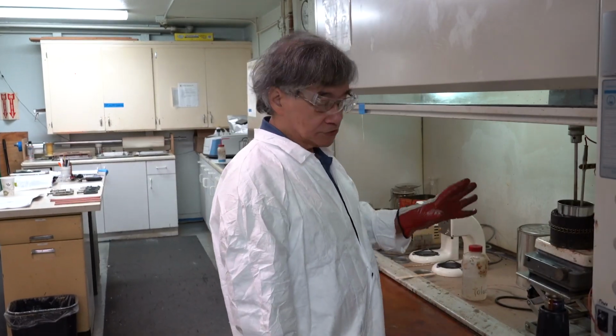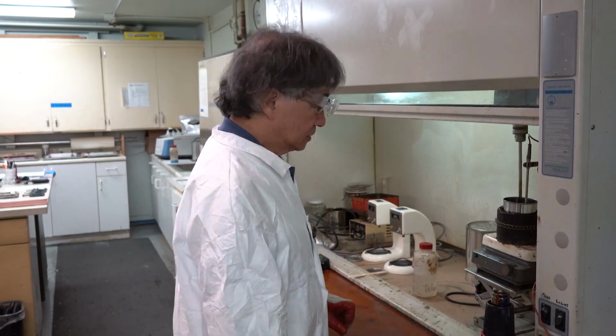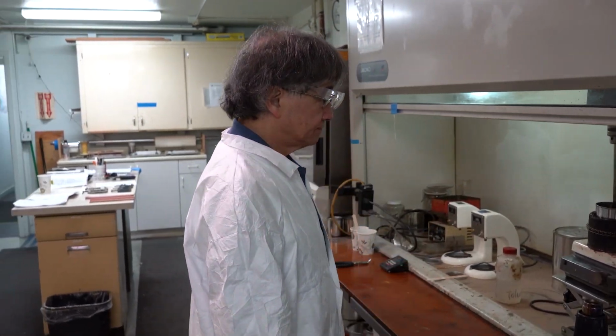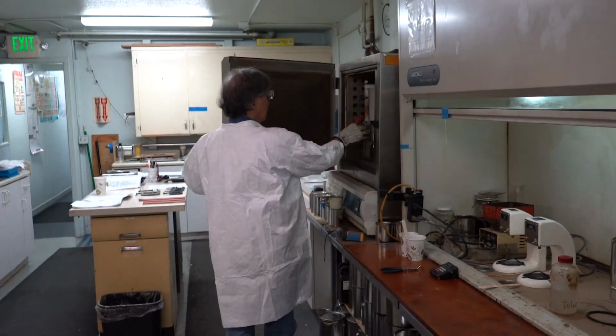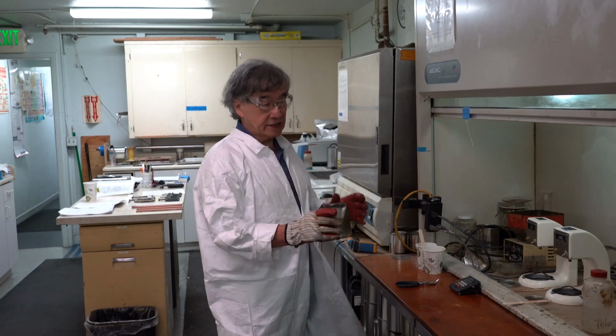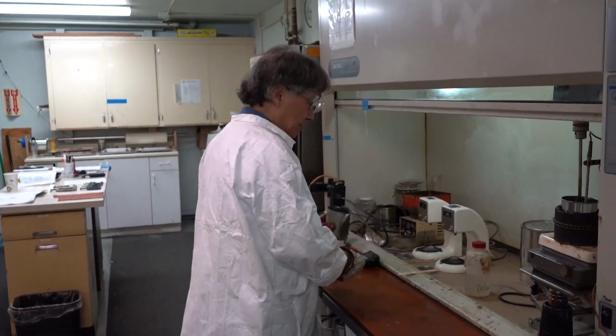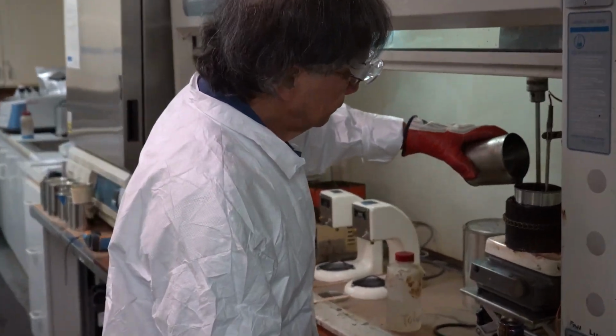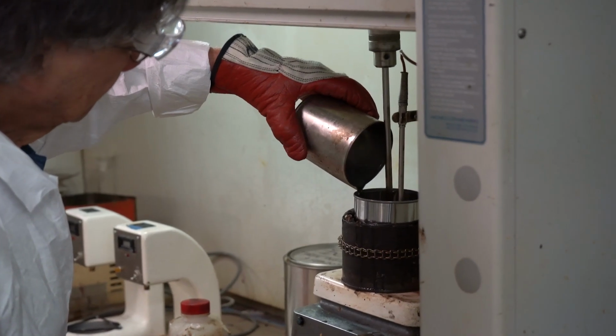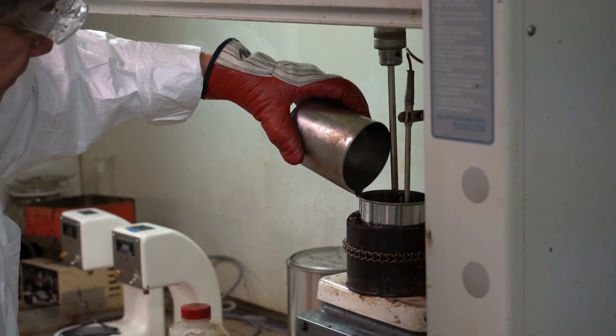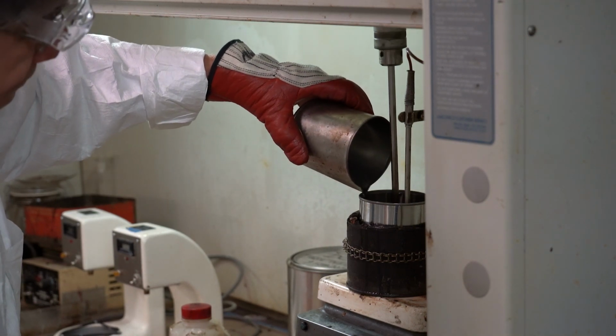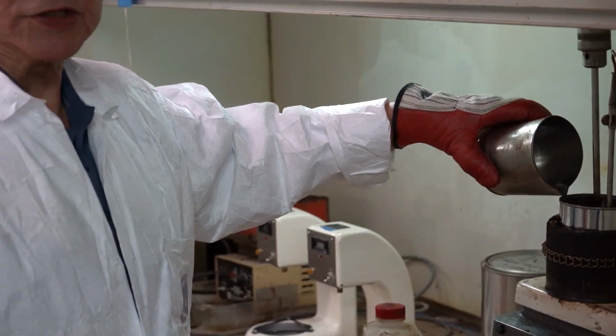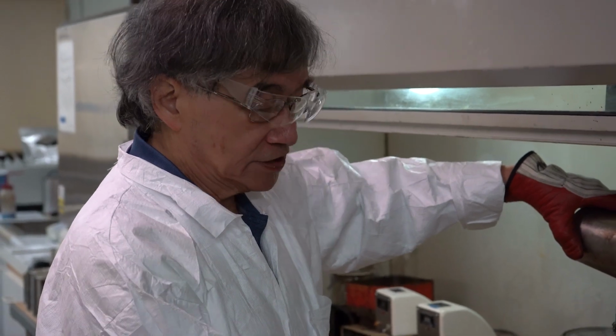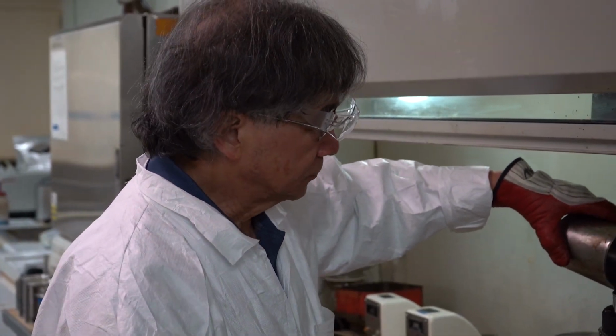So at this point, the temperature is around 250 degrees F or 121 degrees Celsius. I'm going to be mixing Part A into Part B, which is being stirred right now in the stirrer. So the Part A has been in the oven to reach the temperature, and now it is. And I just pour it in. And the amount of Part A has been pre-measured, but then after pouring it in, I still have to remeasure the tare weight to make sure that everything is gone in. If not, I just use the heat gun to chase down the final several drops.